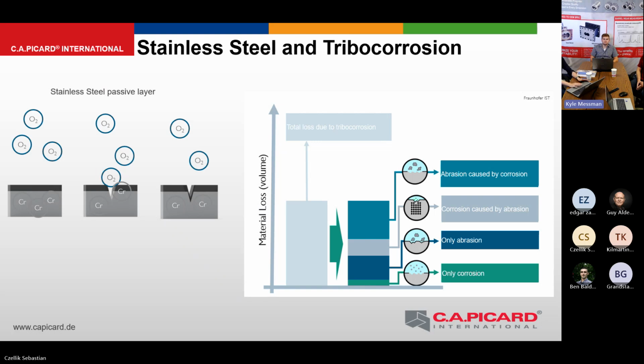What is very hard to forecast are the other 2 parts, which are the main parts of the tribocorrosion, and that's corrosion caused by abrasion, so that you hurt the lattice and things like that. And because of that, corrosion can start. And the largest part is abrasion caused by corrosion. That means we have abrasion because the corrosive products can be removed very easily.